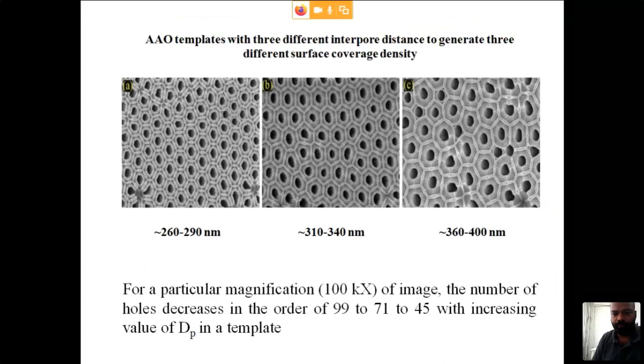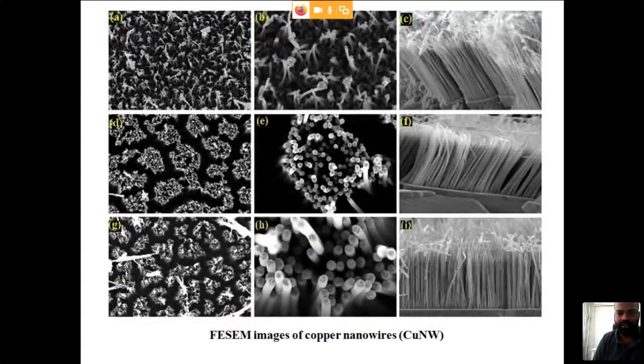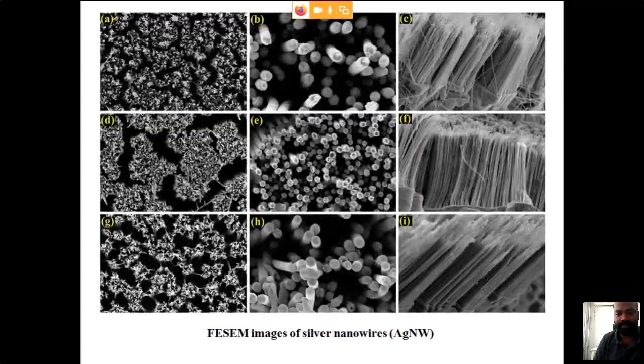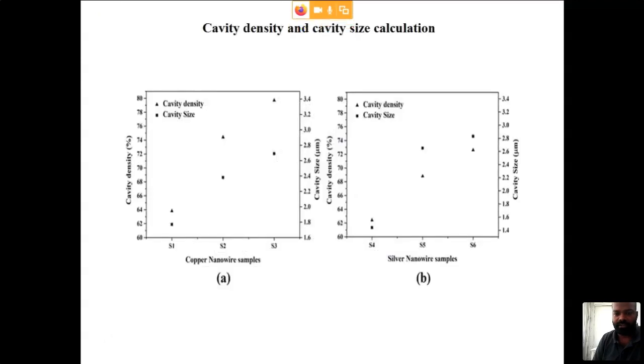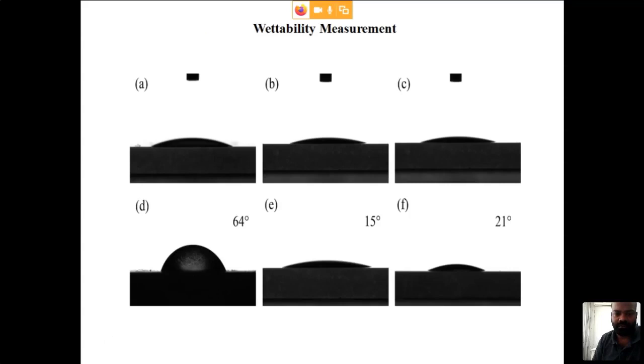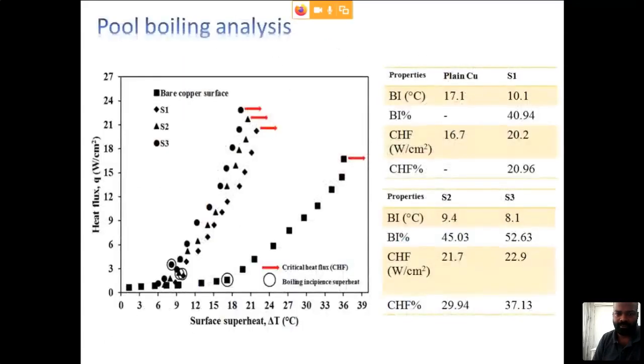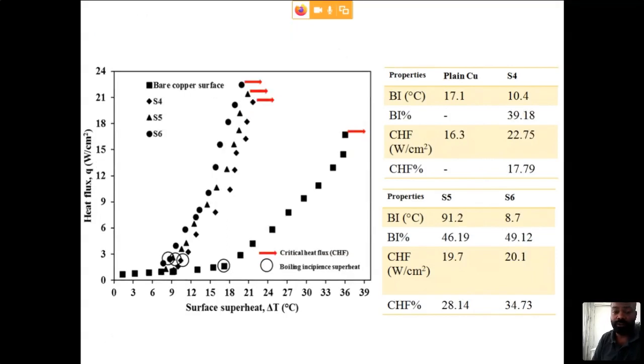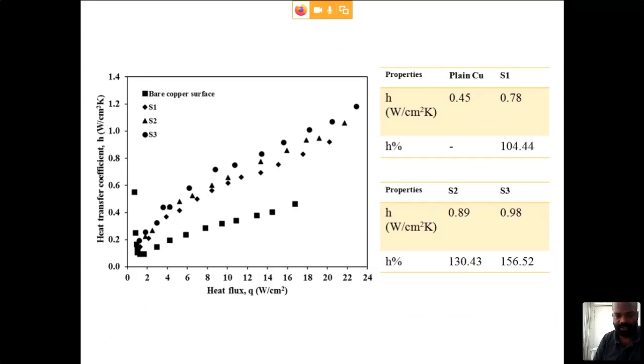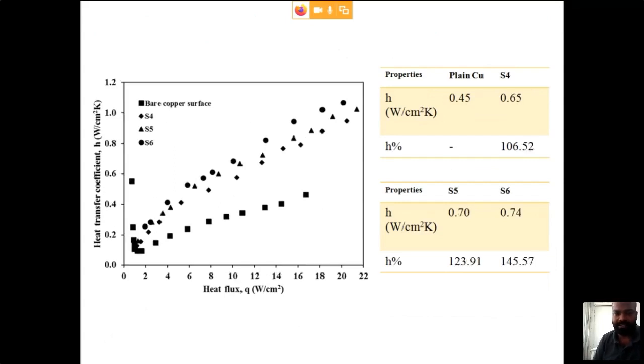And then we have used different distances between nanowires. You can see here that using the matching template, the distance between the nanowires is increasing here. You can see the variation in their packing. And again, using this, this is a contact angle measurement we did, a surface roughness measurement, and pool boiling analysis. Again, we got improved performances, but all the improved performances were comparable with each other. But as compared to the plain copper, the performance was very high, both in terms of heat flux as well as heat transfer coefficient. We used both copper nanowires as well as silver nanowire.